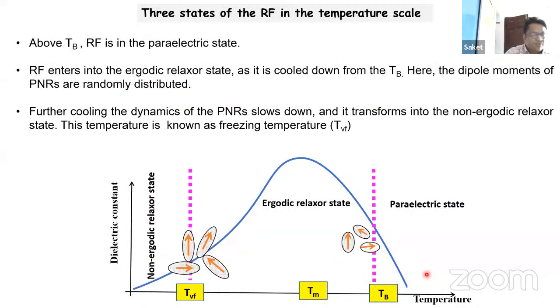So suppose in the paraelectric state, why is it showing the diffuse transition? Here in this dielectric permittivity versus temperature plot, in the paraelectric state, at a particular temperature, which is called the Burns temperature, below that there is a formation of small regions at the nanoscopic length scale where the dipoles are. They will form at a particular temperature, and with decreasing temperature they will start freezing. They will grow and they will freeze. You need not worry about the words written, ergodic and non-ergodic. That may be a little deeper.